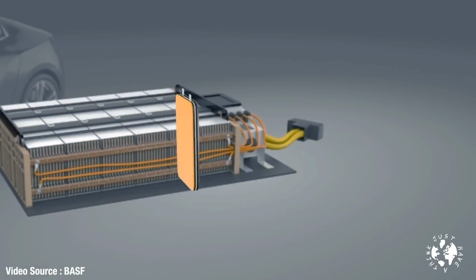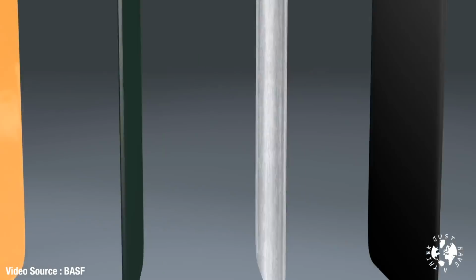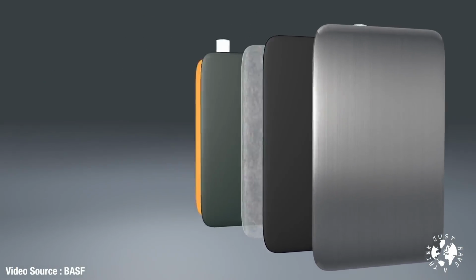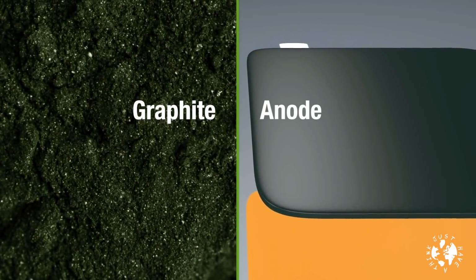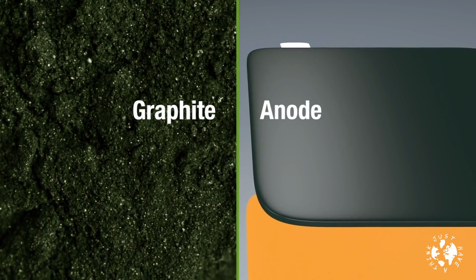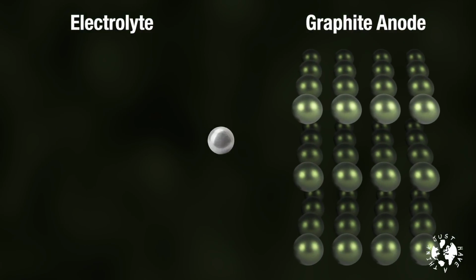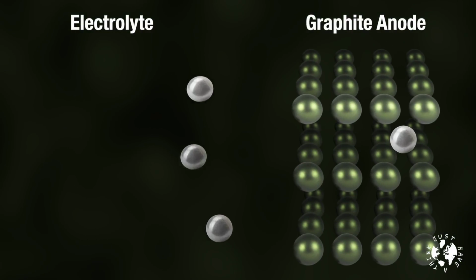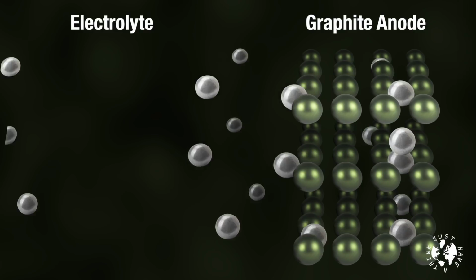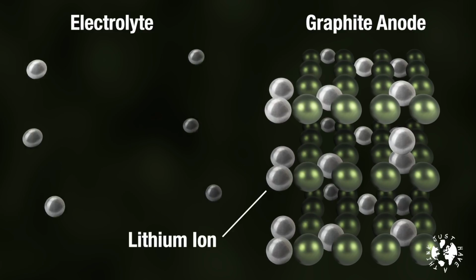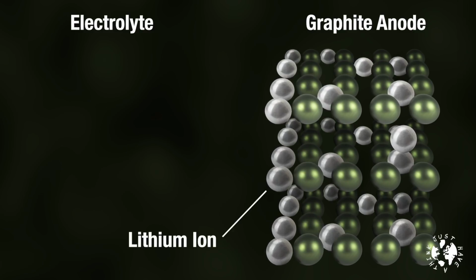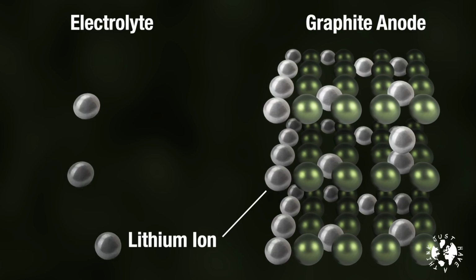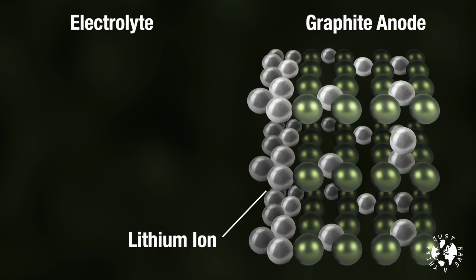Current lithium batteries mainly use graphite for the anode material. In the charging process at normal temperatures, some of the lithium ions intercalate or interweave with the graphite layers, but some of them get stuck to the surface of the electrode, causing this plating effect. As the rate of charge increases, more of the lithium ions tend to plate the electrode and less of them get involved in the whole intercalating thing.